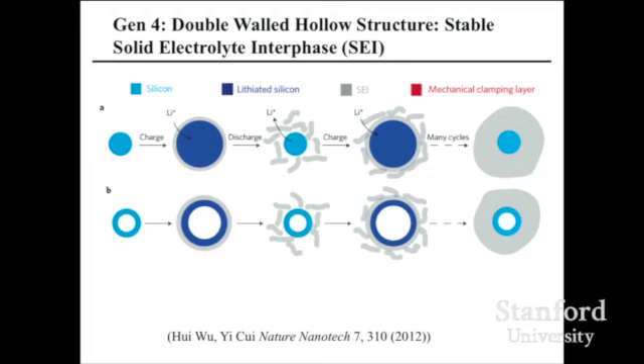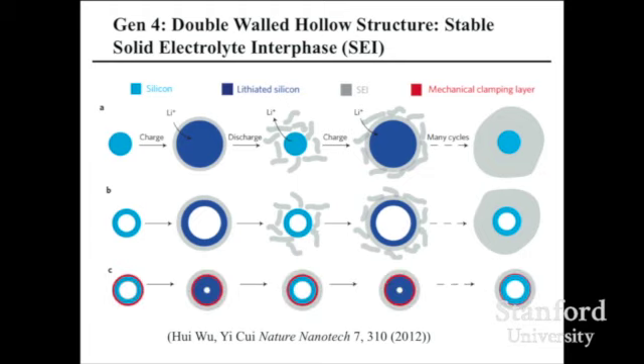So this became a really tough problem for several years, until one day we came up with this idea. What if I make a hollow structure? On the surface, I put in this red color coating. Mechanically very, very strong. So lithium can still come in to react with silicon, the blue color.